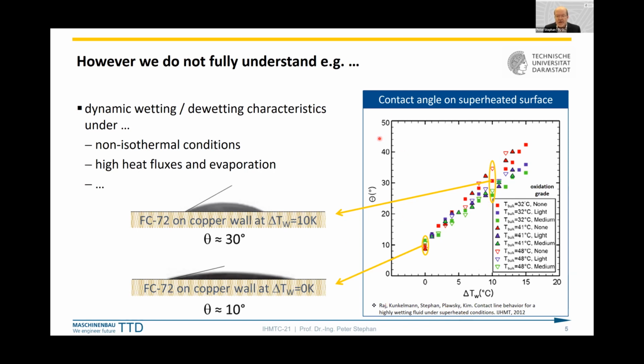Here we plot the measured apparent contact angle depending on the wall superheat. Zero superheat means the complete system is isothermal. We put an FC72 perfluorohexane droplet on a surface, on a copper wall. With delta T of zero, no superheat, we measure approximately 10 degrees contact angle.